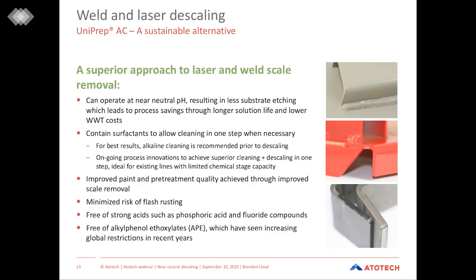For the best results, alkaline cleaning is recommended prior to descaling to remove the organic soils that are present on the part before doing the inorganic scale removal. But ongoing process innovations to achieve superior cleaning and descaling in one step are underway. And this is ideal for existing lines with limited chemical stage capacity. This would potentially allow applicators to not add additional stages to their application, but use a descaling chemical like Uniprep AC as a drop-in solution for both organic and inorganic removal.